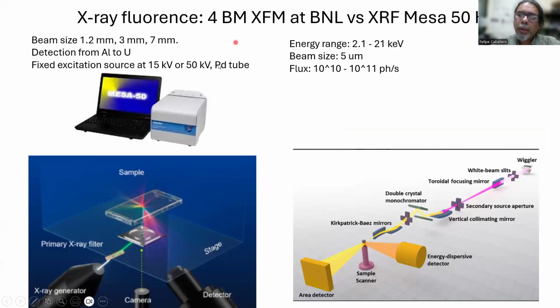In the previous part of the study, we used X-ray fluorescence using benchtop equipment that has a large beam size. It analyzes spots of 1.2 millimeters, 3 millimeters, and 7 millimeters with a fixed excitation source, 15 kilovolts or 50 kilovolts only. And in the case of synchrotron-based X-ray fluorescence at the 4BM XFM beam line in Brookhaven, there is an energy range from 2.1 to 21 kiloelectron volts. But we have a spot size of 5 microns, so there is a lot of spatial resolution here. And also there is a very large flux of photons that reach the samples, so the limit of detection is very low. We can see parts per million of the pollutant. That is not very possible with benchtop equipment with high resolution.